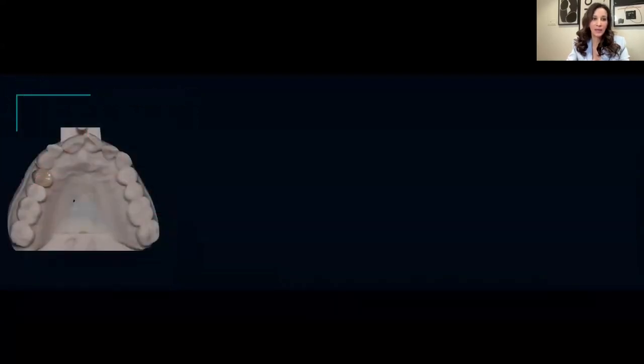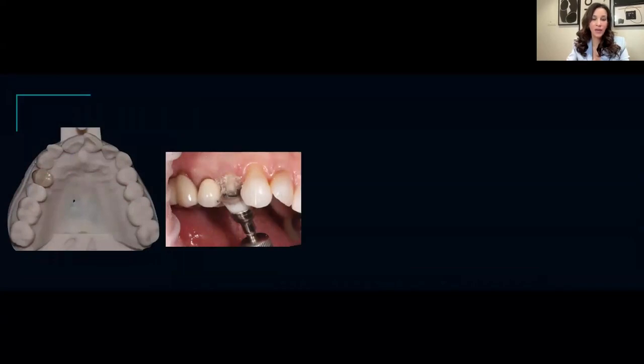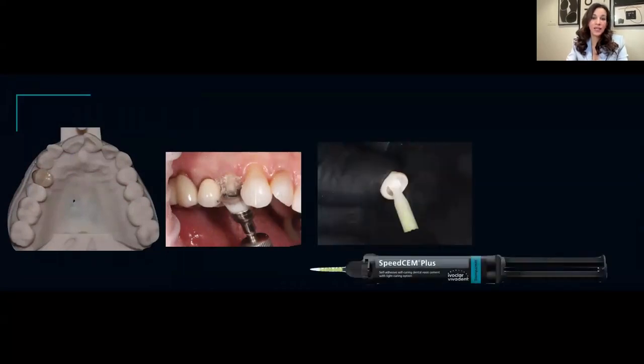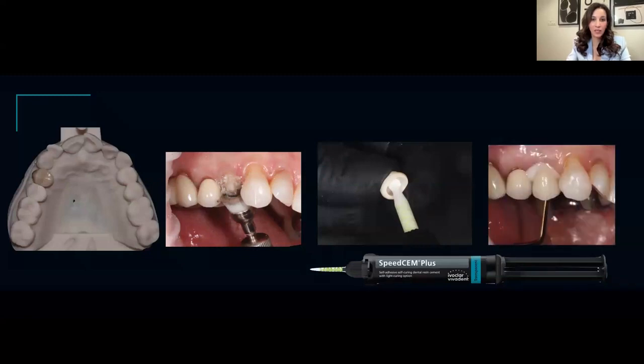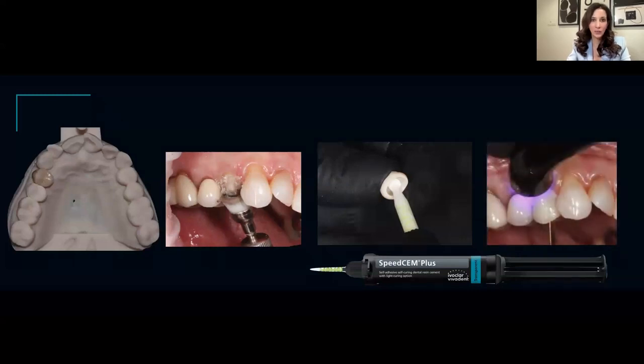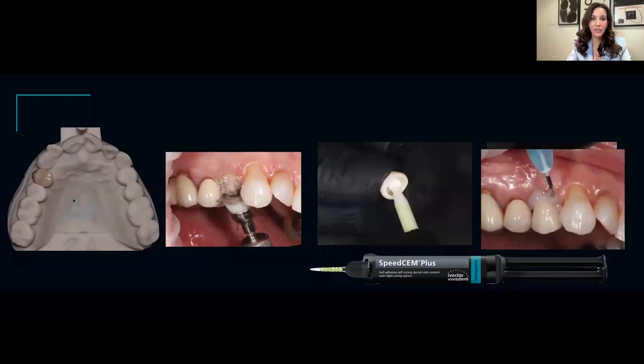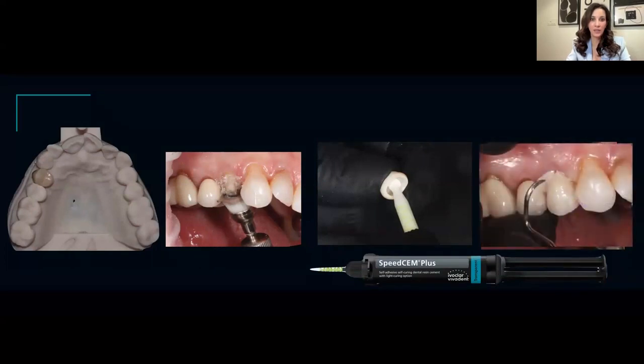This happens to be an Emax crown. We have the crown, we want to pumice the tooth, and then we just take the crown and load it. In this case, I used a SpeedCEM, which has the MDP primer already in it, and then seat it accordingly. And so that's really the way you do it. You can see it's no different than using a conventional cement, but unlike a conventional cement, you have the bond characteristics of the self-adhesive cement in there. And you can also use a glycerin gel that allows for oxygen inhibition, the layer not to be disturbed, and then just cure through that and finish it off.